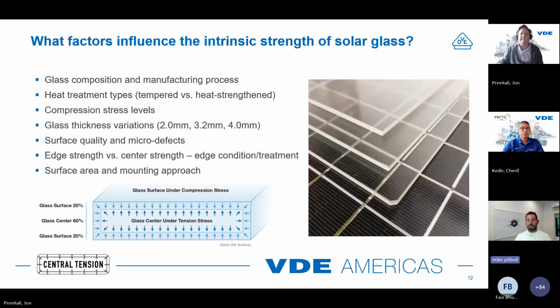But to start, glass composition and manufacturing process, this is to make the large sheets of glass. There are many different types of glass, primarily for the solar industry, and this also goes to architectural and automotive. Soda lime silicate is the primary glass used. For solar, it would be a high transmission or what we would call in the field low iron glass. If you looked at the edge of glass and you see a green tone, that's iron at very small parts per million in it. If you look at solar glass, you'll see a water clear edge, which means high transmission. The iron doesn't absorb any light coming in, so it can maximize the efficiency of solar.